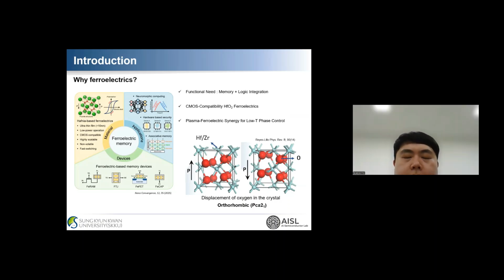However, achieving ferroelectricity requires the stable formation of the orthorhombic phase. Conventionally, this phase requires high temperature annealing above 400 degrees, which limits its applications in 3D integration and flexible device. Therefore, in this work, we investigate whether plasma can induce the orthorhombic phase at low temperature.